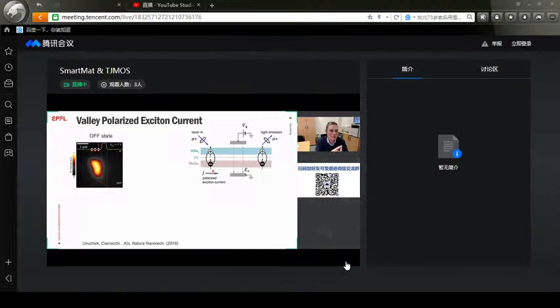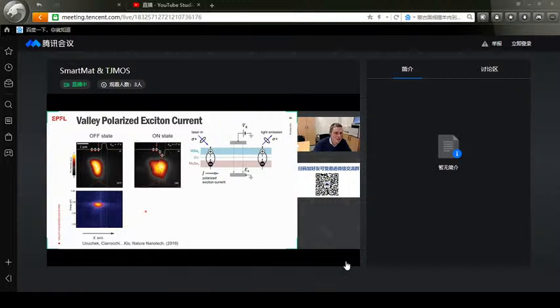So we have combined both the exciton current control and the exciton spin control in one type of device, which was actually a huge step forward, because now we have a valleytronic device, except that it works with excitons and not with single charge carriers. So with this, we can manipulate the currents, as we said, and we can directly record the energy of these exciton clouds.